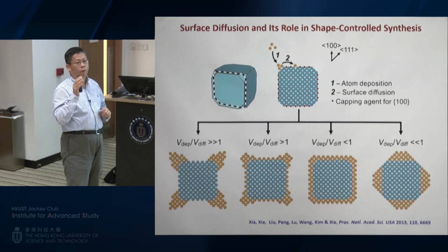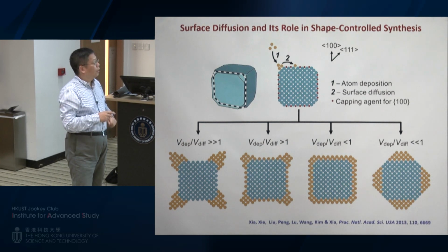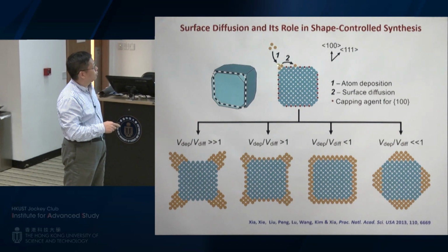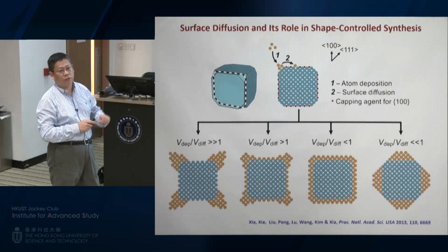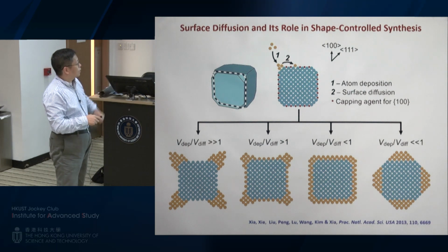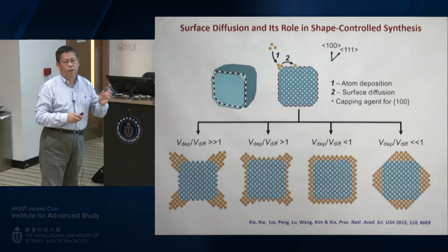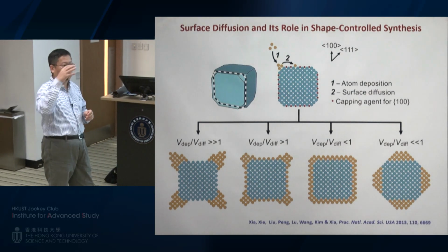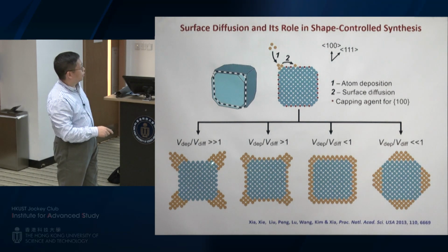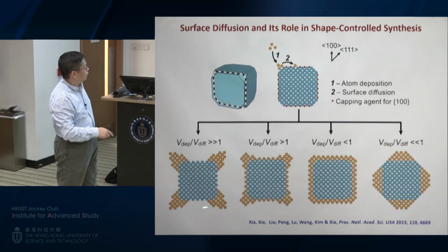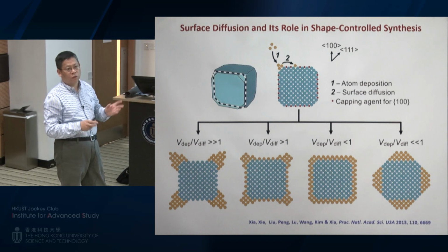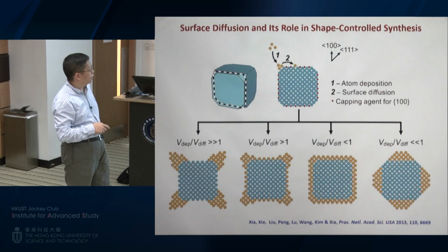So now when you add more palladium precursor and the reducing agent, you are going to generate palladium atoms that will be deposited onto the corner sites first and then diffuse to other areas like edges and the side faces. So in this case, it turned out to be very important to consider the kinetics. If the deposition, you can imagine, is so fast compared to diffusion, basically the atoms have no chance to diffuse to other areas before the next round of atoms come to the surface. So you can see the atoms will be piled up at the corner sites. So eventually the morphology of the final product will be octopods. At each corner you are going to have an arm or branch being formed.